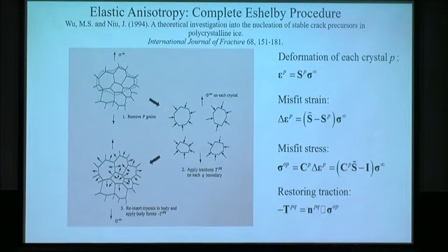So we follow the so-called complete Eshelby procedure to look at the stress concentrations that could arise in the vicinity of triple junctions of grains that have random z-axis orientations. So what is this about? This procedure is used to calculate the stress concentrations. We isolate a number of grains, for example 1, 2, 3, 4. So we have 4 grains within the polycrystal, and under some loading, it could be tension, compression, or any loading.